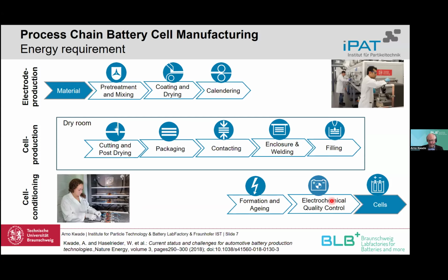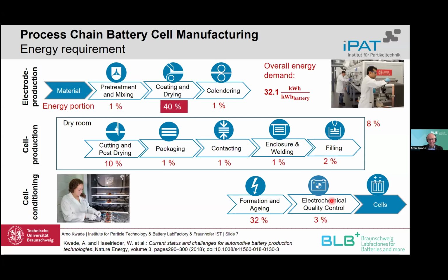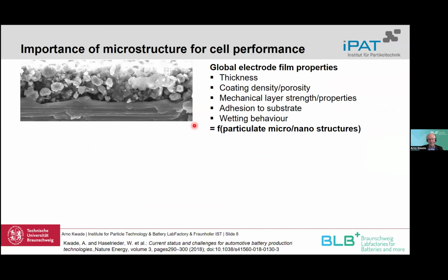And if we now look at the energy consumption of the different process steps, you can see that the highest energy consumption is in the coating and drying, especially the drying step. So it's about 40%. You can find also some other values, but they are still in the range of 30 to 50% for coating and drying. And then also the post-drying needs some energy, and also the operation of the dry room. You see that these are very crucial steps, especially also for sustainability. So we also focus on these steps a lot.